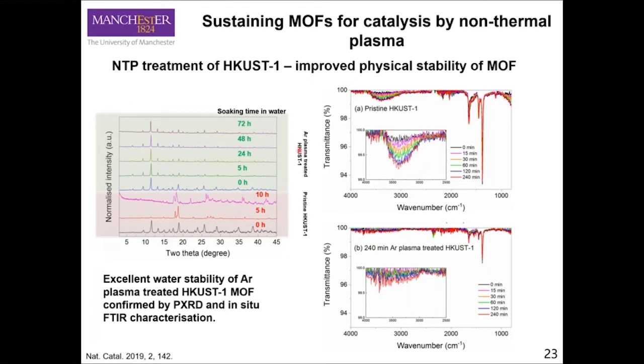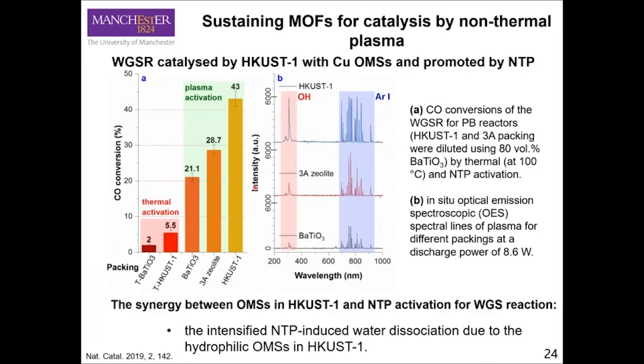So we tried it, and we only give you the selected characterization. We show that it doesn't matter about the non-thermal plasma treatment. We can retain the physical and also chemical properties of the Morphs after the treatment, and therefore have the confidence to go ahead for the catalytic experiment. And we show that by using this material, indeed, it is a very good catalyst.